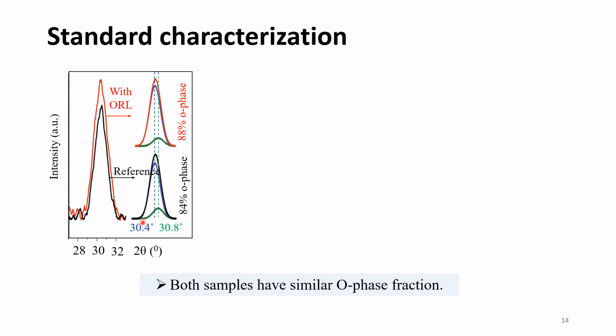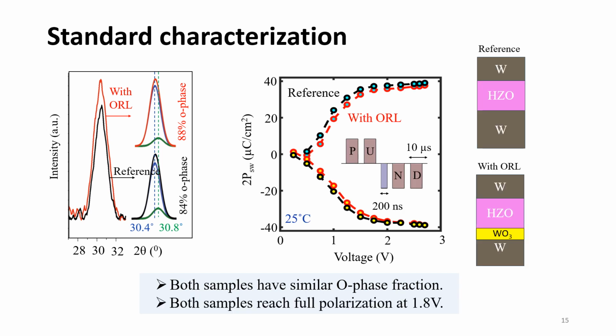We did GI XRD scan on the HZO film of both the reference and the ORL device, and we could see that both the films have comparable amount of orthorhombic phase fraction in them, which means that we are not losing any ferroelectric properties due to having the tungsten oxide layer in the ORL device.